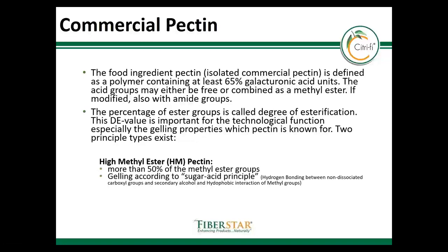The gelling is by a sugar-acid principle. Under acidic conditions, carboxyl groups are not dissociated, sugar binds water, and the polymers can form junction zones. The hydrophobic interaction between the methyl groups supports this binding. Keep this in mind because this natural pectin type is present in citri-fi.